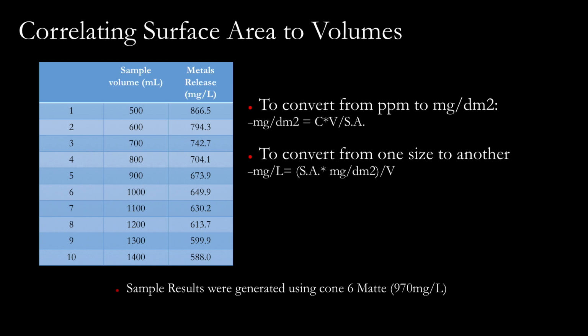As the volume increases, you'll notice that the metals release begins to decline. The larger the piece, you would think, because you have more glaze available, more glaze for attack, that you get a higher number. But the inverse is actually true. The ratio of leaching solution to the surface area dilutes it down to lower concentrations. So your real highest values are going to be from your smallest cups. Kind of interesting, I think. The values for the metals release in this case were used from that cone 6, very, very high 970 milligrams per liter, scary range. But you can see as you increase in your vessel size, you're actually getting less and less volume.